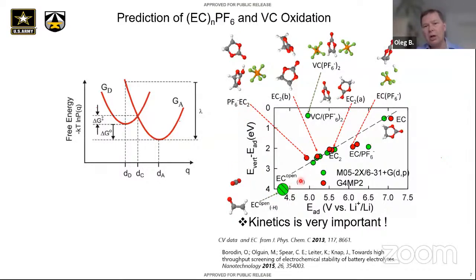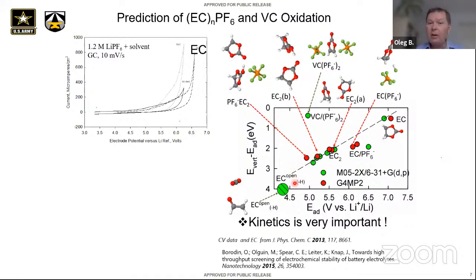Kinetics is going to be the slowest here. As we go to higher and higher potentials, some other reactions will be activated, and they will have a much lower reorganization energy, lambda, and therefore much higher kinetics. If we come with this point of view, then we can compare with CV performed on glassy carbon, which was done in our branch. If you take 1.2 M LiPF6 in an EC solvent and measure CV, that's in microamperes current, pretty small. And you can see that indeed current starts picking up at about 4.3 volts, keeps going up, and there is a very well developed oxidation for EC at about 6.5 volts. So roughly, that's a pretty good picture.